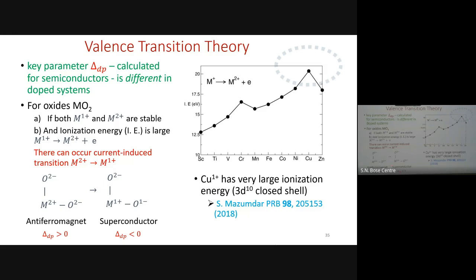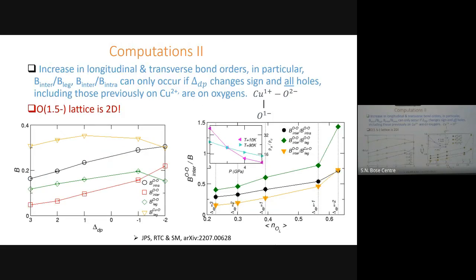So what I claim is that this will have delta dp less than 0. So let's go back to the Hamiltonian and calculate the same dimensionalities, same bond orders, but now I'm changing delta dp. Delta dp goes from positive to negative. The holes have moved from copper to oxygen, and see how fast this quantity, which was flat, rises. All the other bond orders, these are the ratios. You see a distinct change in slope here.